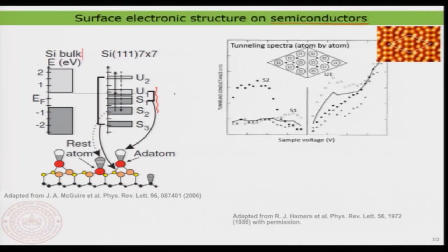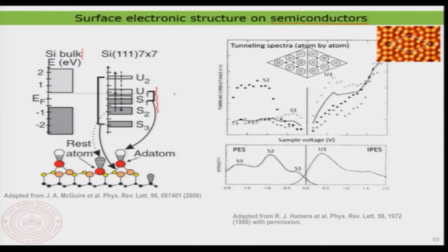We have already seen that in the STS. We have seen that we can measure individually by just moving your tip next to an atom, and you can measure the electronic structure in an extremely localized fashion. That means at an atomic scale we can measure. And we have also discussed that this is quite important, because you can clearly understand the origin of these different kinds of electronic structure, or where they are originating, and so on. But now I also want to make a comparison of the STS that you measured to a photoelectron spectroscopy. Well, this is actually known as inverse photoelectron spectroscopy. We will study that in a minute.